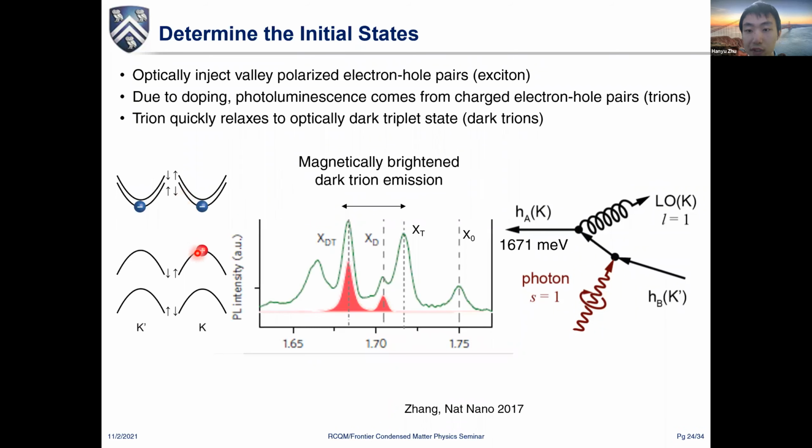So using spectroscopy methods, we can identify that once we inject holes, those holes have a certain energy that is basically a combination of one hole and two electrons in the conduction band minimum. So this system is good because if you look at the spin, this is a spin triplet state. So once the hole and electrons stay there, they're dark. They don't have this optical transition, so they have enough lifetime for the phonons to scatter those holes. So this is our initial state.